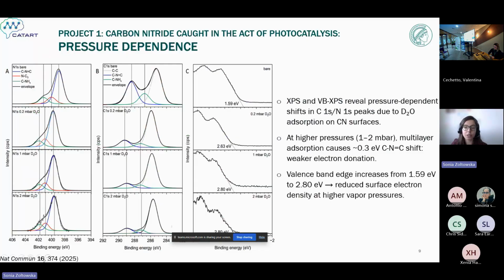And here you can see the XPS spectra of the nitrogen core level and carbon core level at different pressures of water, together with the valence band XPS. And indeed, we can see that for the higher pressures, 1 and 2 millibar of water, we observe multilayer adsorption that causes smaller shifts of the edge functionalities towards, of course, higher binding energies, because we assume there is a weaker electron donation. On the other hand, valence band XPS shows a shift to higher binding energies, like you can see here, from 2.6 for 0.2 millibar of water to 2.8 for 1 and 2 millibar of water. That suggests reduced surface electron density at higher water pressures.